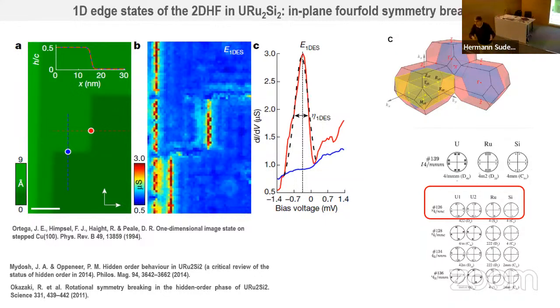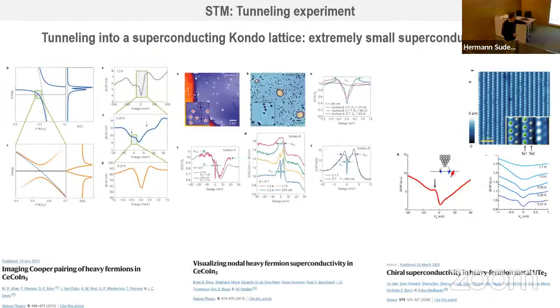So in some sense, these states also help us to understand better how correlations work in this material. So you can, of course, this is the usual symmetries which you find in a tetragonal system. And here you have actually very similar symmetries, but you see that the two uranium planes are not equal. So we can say something about the symmetry using this measurement. And then there is something about the superconducting gap. This system then becomes superconducting and we are measuring inside the superconducting phase. So people think it's a chiral superconductor. So people have lots of different stories for this, which is very nice.